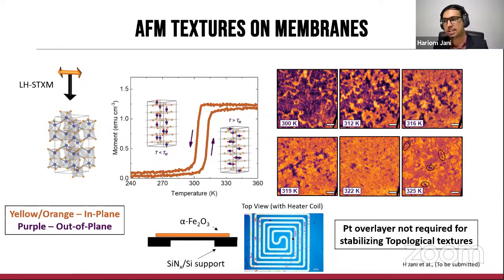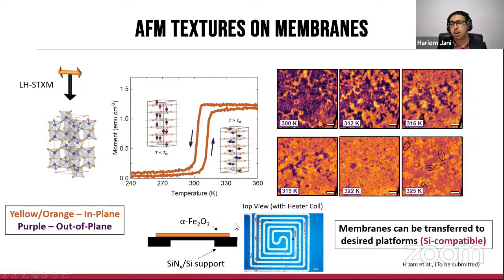This is, of course, not entirely surprising because we know they're emerging because of the Kibble-Zurek equivalent transition. But more importantly, this result actually points to addressing a key gap in these kinds of antiferromagnets, because oxides are not necessarily very compatible with silicon nitride because of their growth conditions and so on and so forth. But because they can be grown as membranes and they can be transferred, it could be possible to make these objects eventually silicon compatible and more controllable in the kind of platforms that are usually used for devices. A lot more development is required here, but this is definitely the first step in that direction. Also, it is then possible to do all kinds of interesting in situ experiments, but I'll skip that for now. I just wanted to highlight the fact that it's possible to do with membranes.